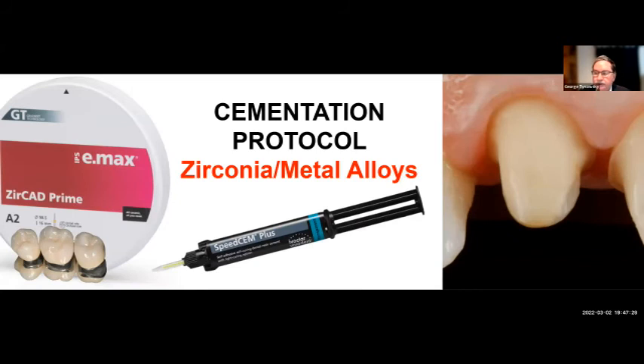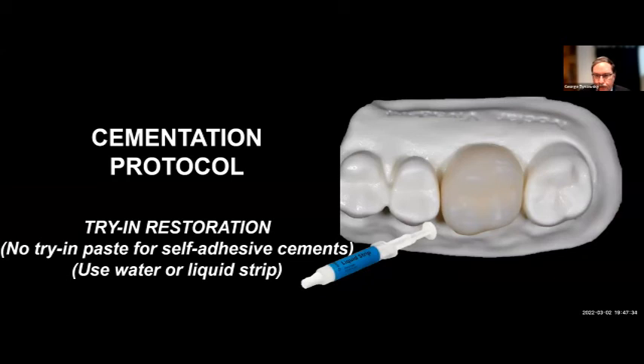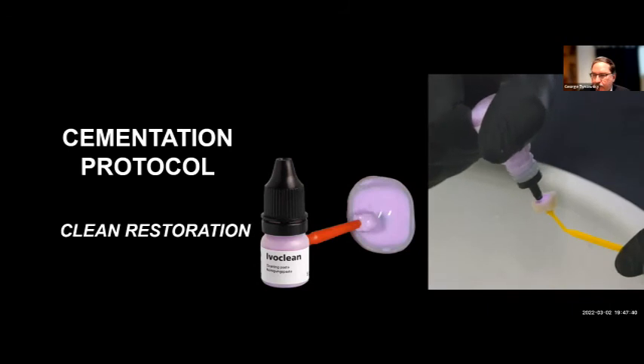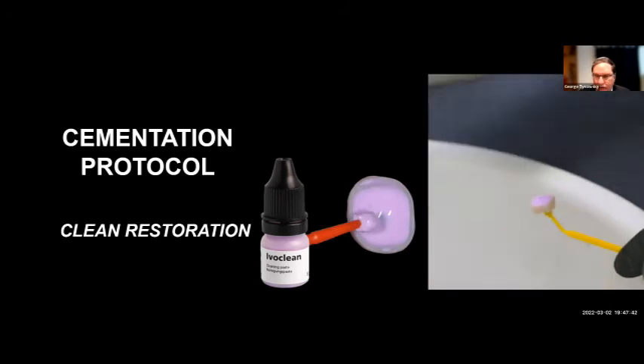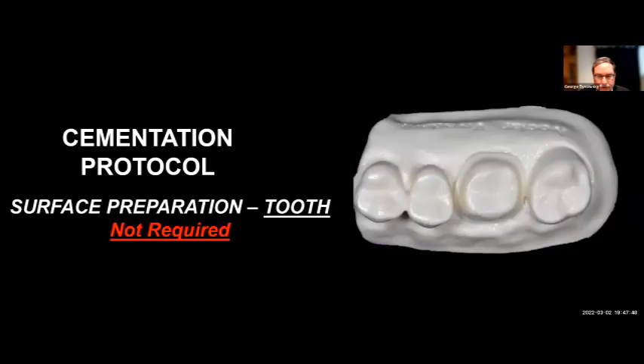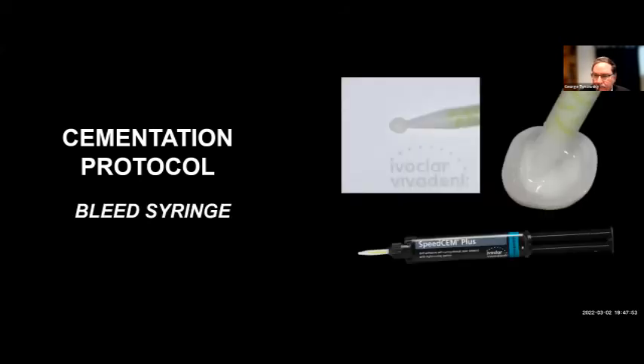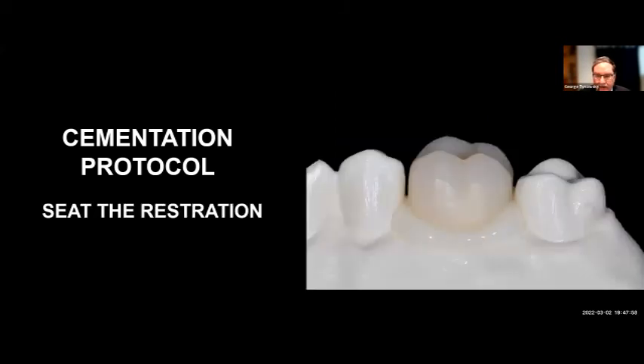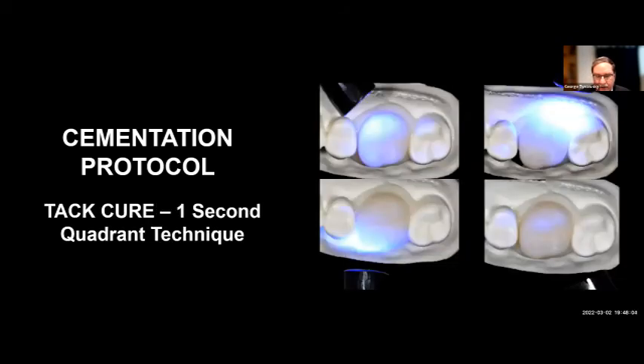So what you'd have here is a crown prep. You basically have your cement. Let's take a look at it here. You try it in. Basically, you'd clean it out accordingly with the IvoClean that we mentioned before. Let that rinse off the proteins and the excess from the saliva. Surface treatment of the tooth is not necessary because the primers are built into the cement. We bleed the syringe first, then load the restoration, seat it down, and then tack cure it with the quadrant technique. So again, interface dynamics to make sure that we have the proper sealing of the restoration.